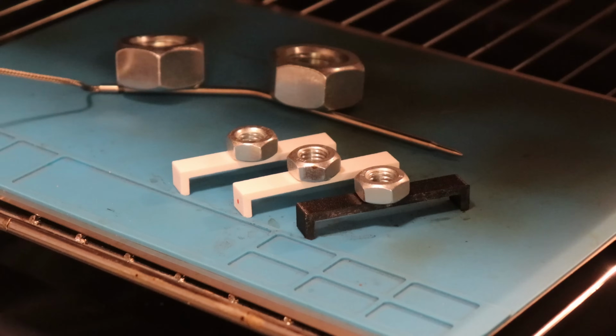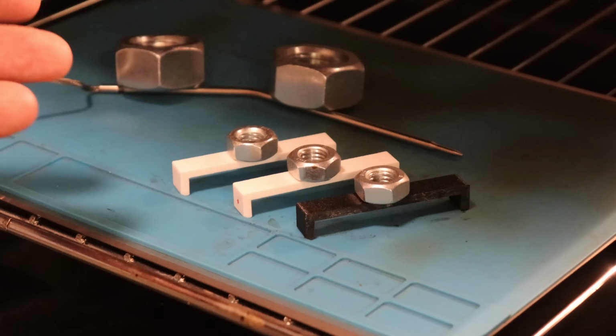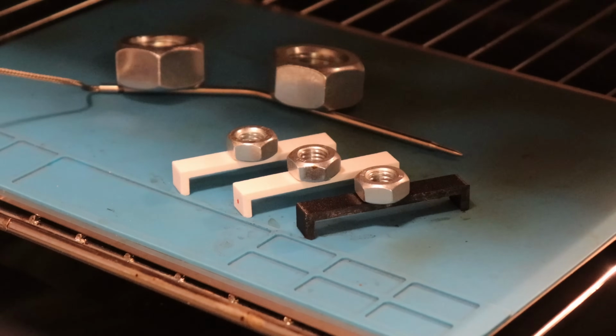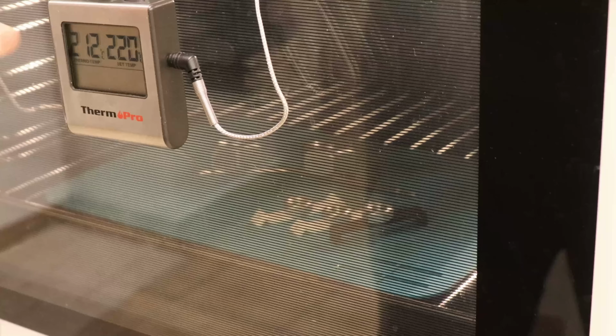Temperature test in the oven, and maybe these two white objects I have to take out earlier, but we will see soon. Speed up time-lapse video, and those two white objects are from my previous testing, the ABS and ASA, but this PETG-CF doesn't want to start with the forming. I have to stop the experiment, 212 degrees Celsius.